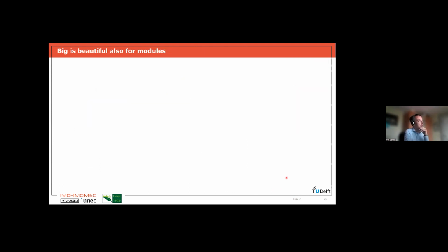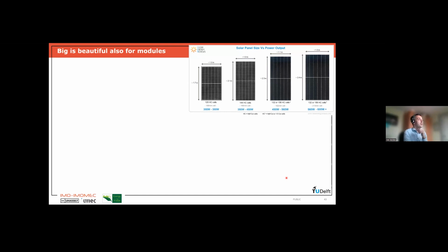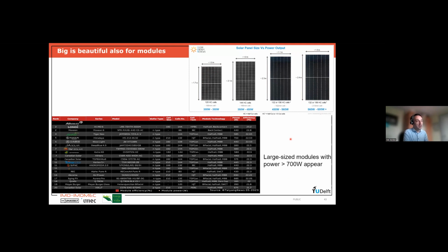Now, some evolution in the modules. Also here, the module size has increased a lot because, of course, the wafers have been increased. If you make a 60-cell module with wafers of 156 millimeter, or a 60-cell module with wafers of 210 millimeter, it's going to be a huge difference. Where in the past, PV modules were typically 1 meter wide and perhaps 1.6, 1.7 meter long, we now see modules which are much longer, let's say 2.4 meters long, and also much wider because they use much larger cells. That also means that not only has the efficiency of modules increased, but especially because of the size, the output of the modules has drastically increased. In the past, we had typically modules with, let's say, 400 watts power, but now these largest modules can easily have up to 700 watts of power for just one single module.